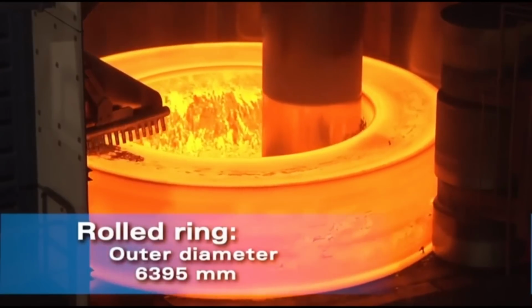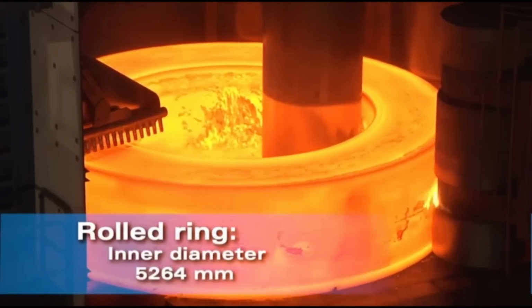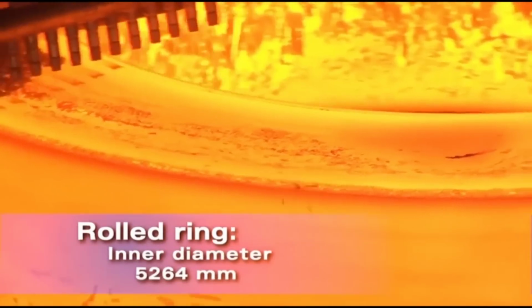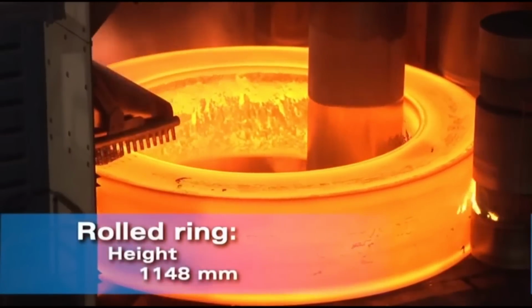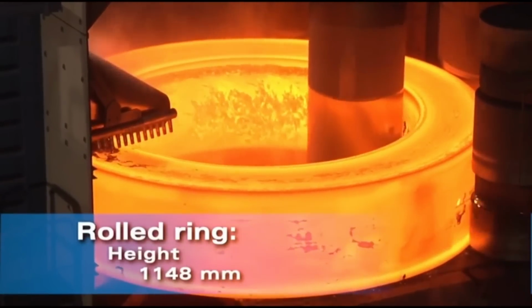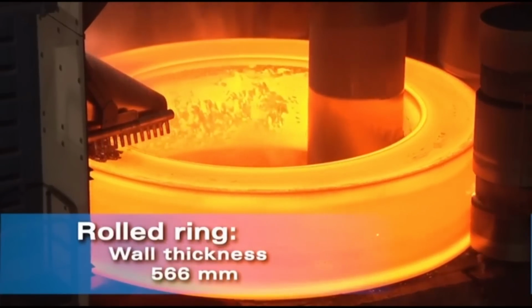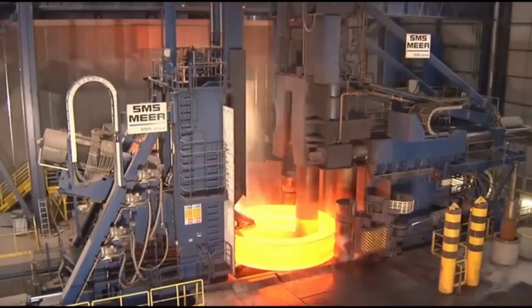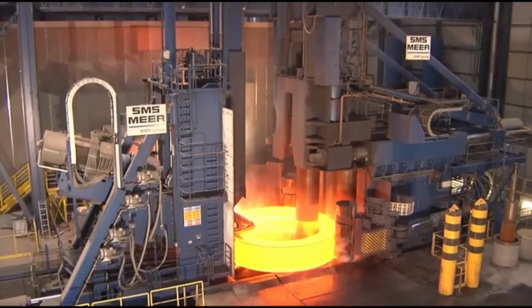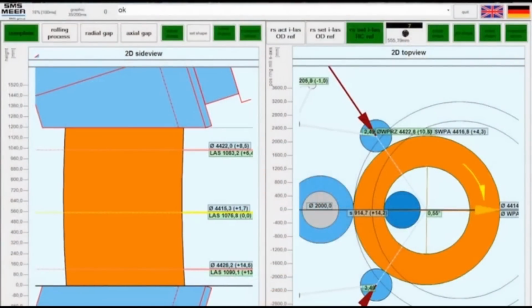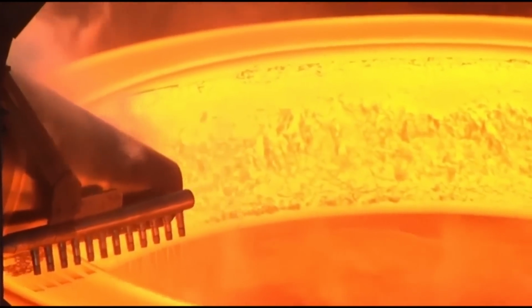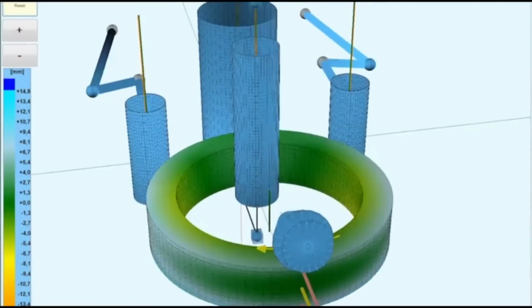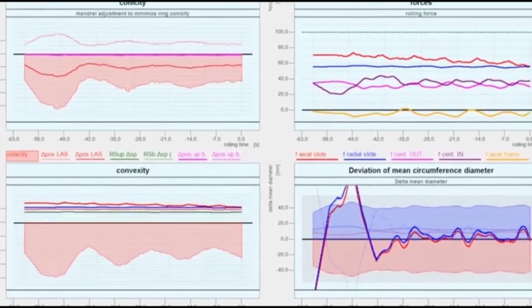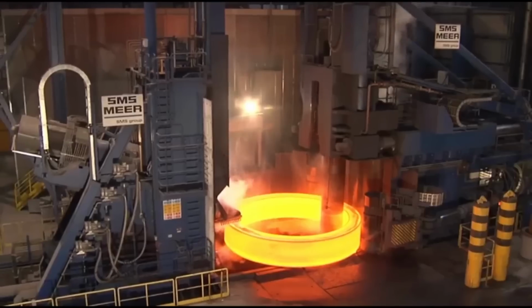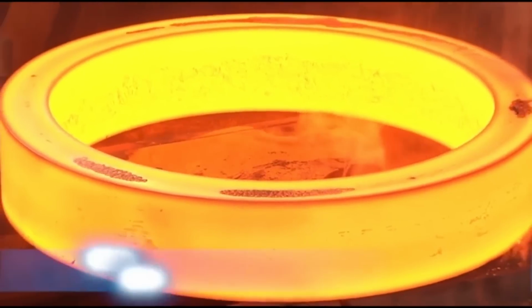Outer diameter, 6,395 millimeters. Inner diameter, 5,264 millimeters. Height, 1,148 millimeters. Wall thickness, 566 millimeters. Post-rolling, the ring's outer diameter expands significantly to 6,395 millimeters, while the inner diameter grows to 5,264 millimeters. The height decreases to 1,148 millimeters, and the wall thickness is reduced to 566 millimeters, illustrating a substantial deformation. This transformation is achieved in 460 seconds, with the final product weighing an impressive 89.3 tons. The longer rolling time and increased weight reflect the greater complexity and effort required to process such a large ring.